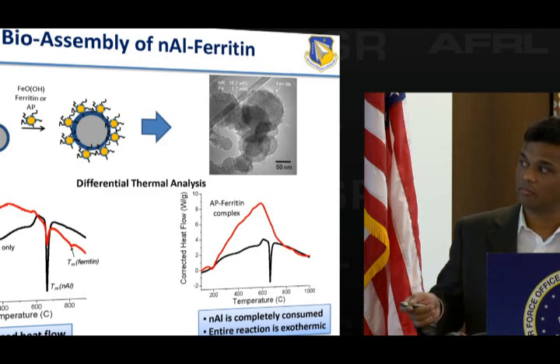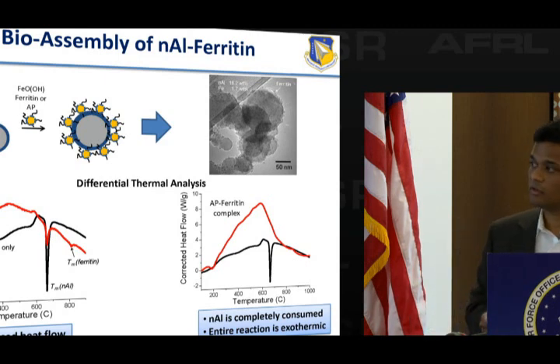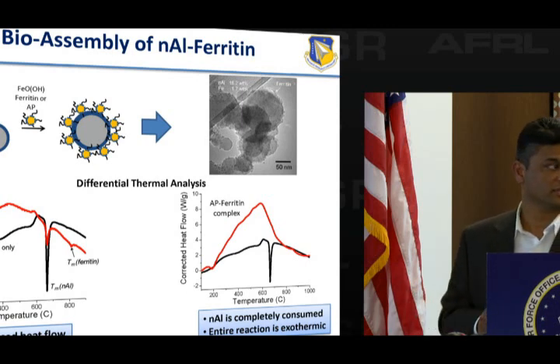And this is just the nanoaluminum by itself. This is the melting that you see from the nanoaluminum. You can see that this is equal amounts, so the peak is reduced here because you get combustion much earlier. This is where the ferritin completely disappears or dissolves, or the melting of it occurs. Now, if you add ammonium perchlorate, you actually see a massive increase in the heat flow. You can see the aluminum is completely used up even before that 650 degrees point is reached.